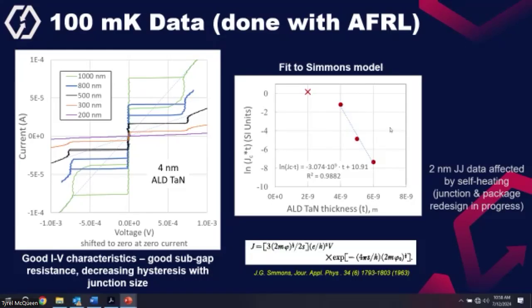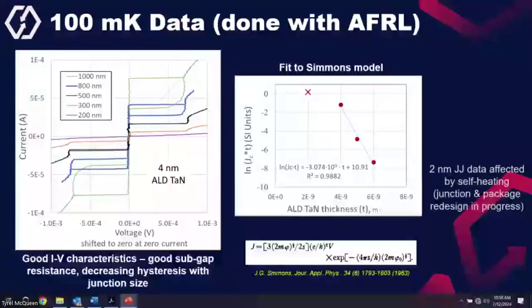Yeah, so packaging is another area where you can think of making your career. Like you can see that cross point, it is for the thinner ALD tantalum nitride because the critical currents were higher. It was having self-heating effect. So we need proper thermalization, like having proper contact with copper, having a better package design in order to reduce all these effects. So we are working on those things. So that is also something to keep in mind.